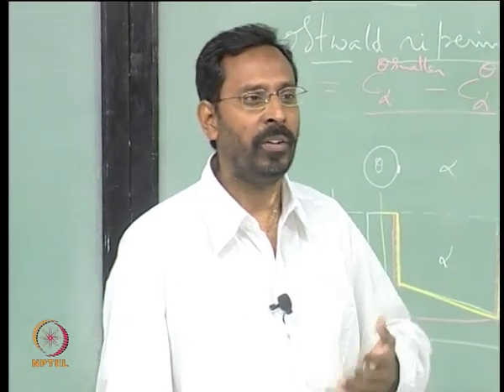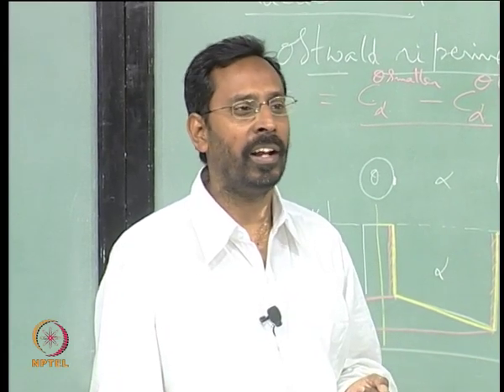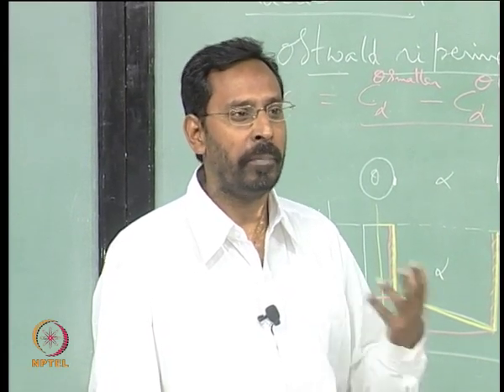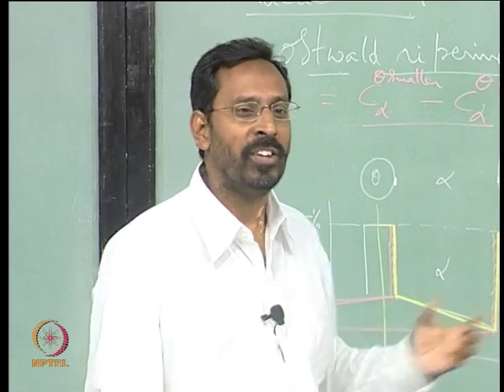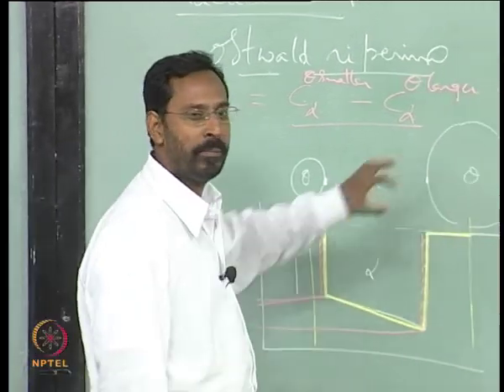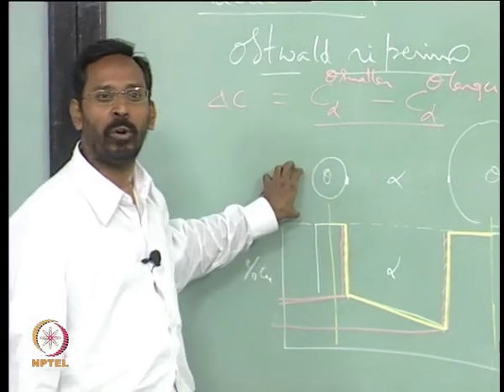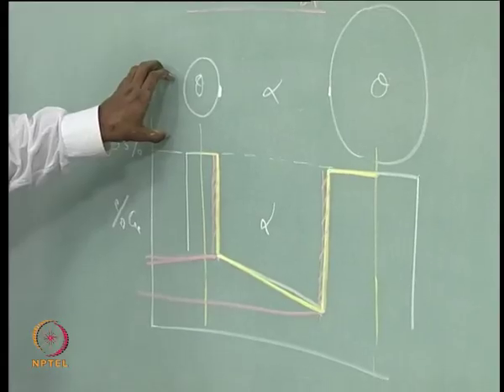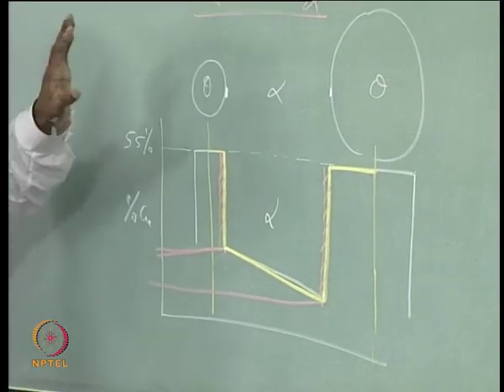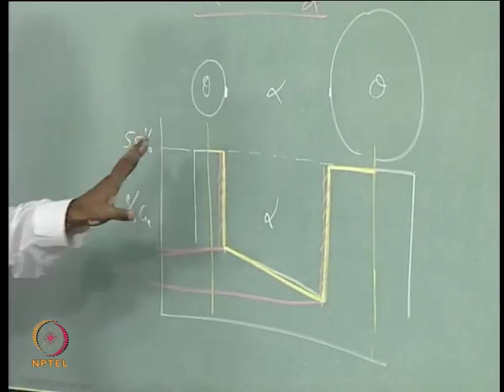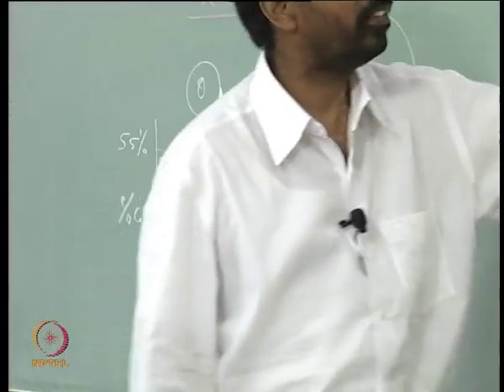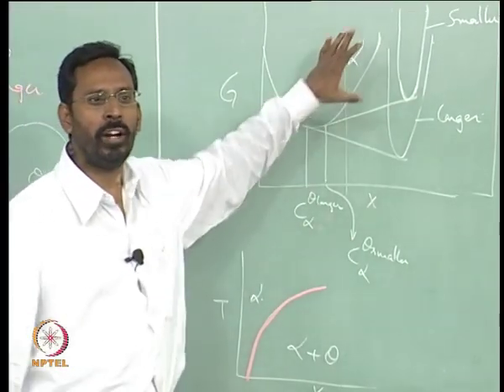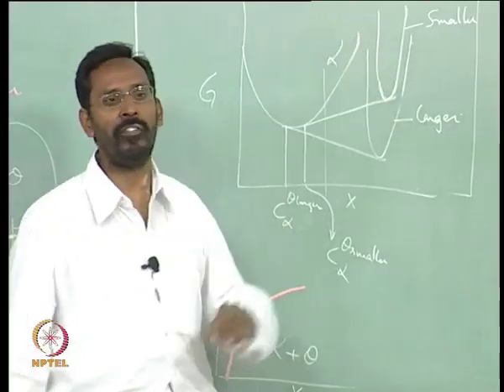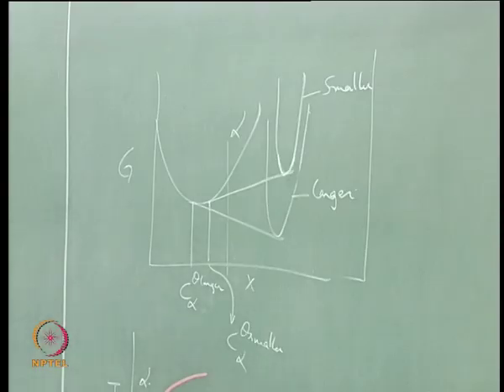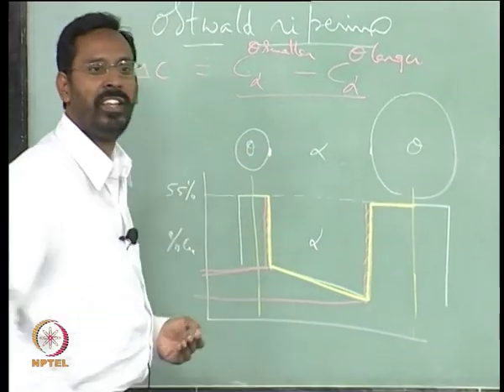It is like we see in typical life, the bigger ones try to grab the smaller ones. So, exactly the same thing is happening here. The bigger particle is just growing at the expense of the smaller particle, and the whole driving force for such a thing is coming from this free energy. So, once you understand that the free energy of different particle sizes will be different, you can easily understand why this is happening, and this gradient starts increasing.